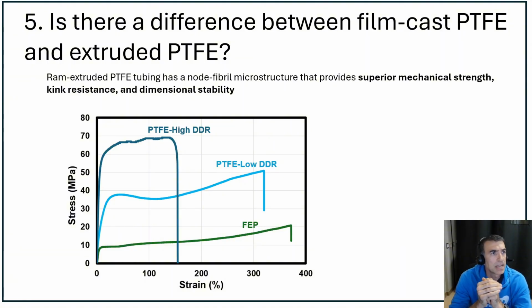Is there a difference between film cast PTFE and extruded PTFE? The answer is yes. When you film cast PTFE, or in general, when you apply orientation, PTFE is very sensitive to DDR, or drawdown ratio, that is applied. And that's because the molecules can orient easily. So if you compare, like in this graph, a low DDR, low drawdown ratio, versus a high drawdown ratio PTFE, the tube that is produced, let's say we are using RAM extrusion for producing the tube, the tube that is produced with a high DDR has significantly higher mechanical properties compared to a low DDR PTFE, and it basically has better mechanical strength.